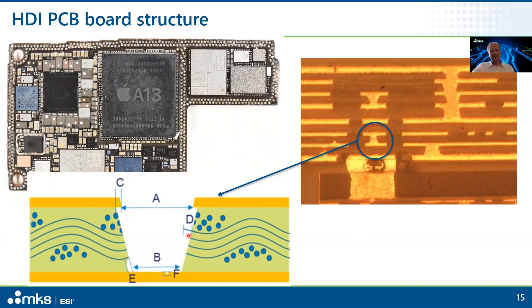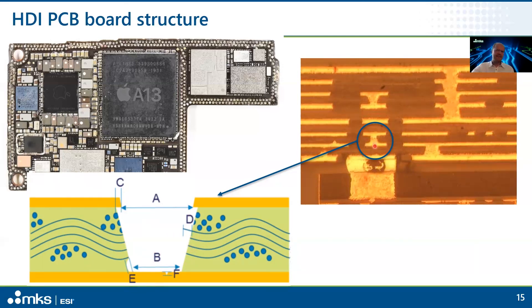So you either need a lot of power to cut through the glass fibers, or a wavelength actually absorbed by glass linearly, which goes up to the mid IR. That's what's typically used: the CO2 laser at 9.3 microns. This has the added benefit that the bottom copper acts as a reflective backdrop, so most power is reflected, creating a nice contrast between the dielectric being removed and the bottom copper not overheating and delaminating from the lower layers.